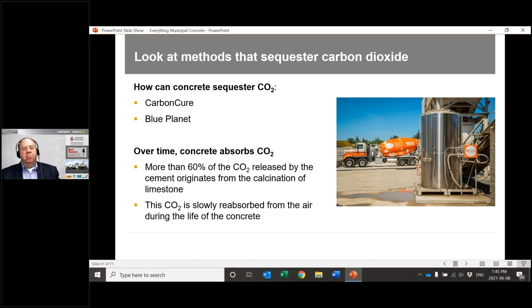We're seeing a lot of new products coming out. So Carbon Cure and Blue Planet, for example. So Carbon Cure adding CO2 directly to the plastic concrete during the production process, positive impacts there. Blue Planet is a company that's using CO2 and crushed concrete to create synthetic aggregate.